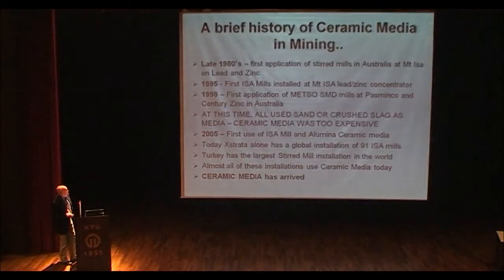And at that stage, working with Isa, one of the major producers today of ceramic media developed an alumina ceramic, and by that we mean it's literally an aluminium oxide, anywhere from 80% Al2O3 with a few other tweaks. And you end up with a little bead, and if it's a good product, it'll be an extremely hard bead. They have Vickers hardness of anything up to 1400, which is way above conventional steels in any form.